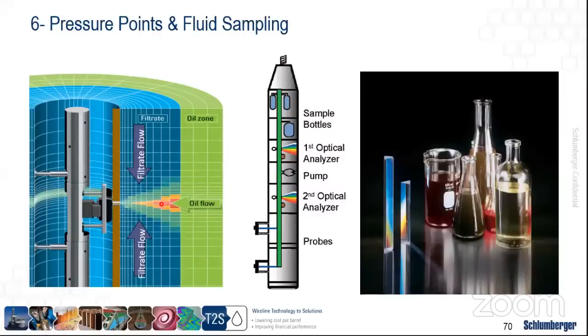Once we reach a stabilized flow, we can start getting what we need, which is the oil coming from deep inside the formation, the virgin zone. The more we pump, the cleaner the sample will be, because we're removing a lot of the filtrate coming from the invaded zone, and the better the quality of the sample and the analysis. This fluid is being pumped up and dumped into the tool. Once we agree that this is a clean sample with less contamination from the mud filtrate, we start to collect the clean fluid samples inside bottles.